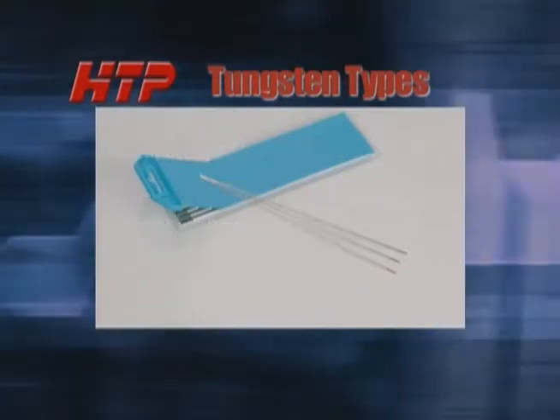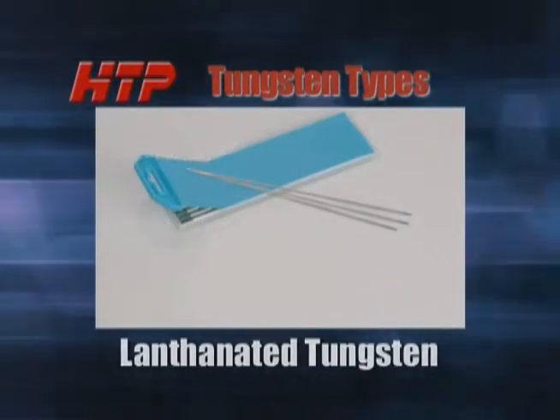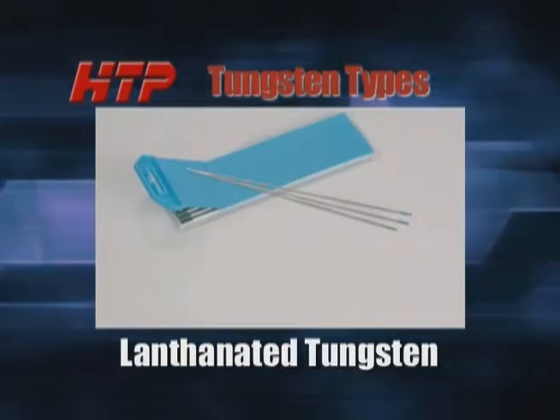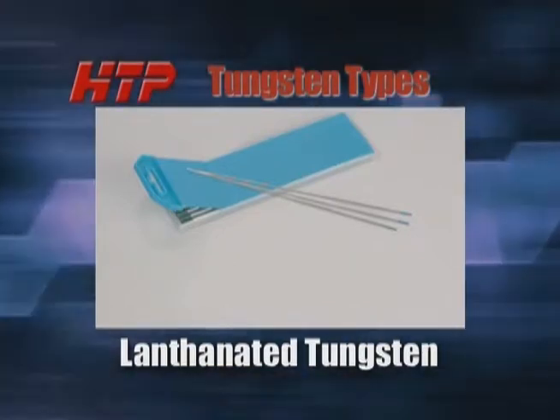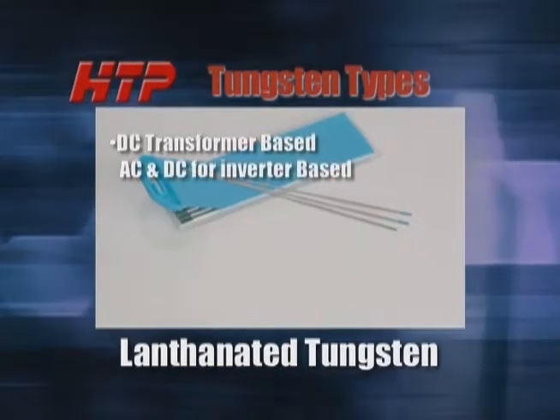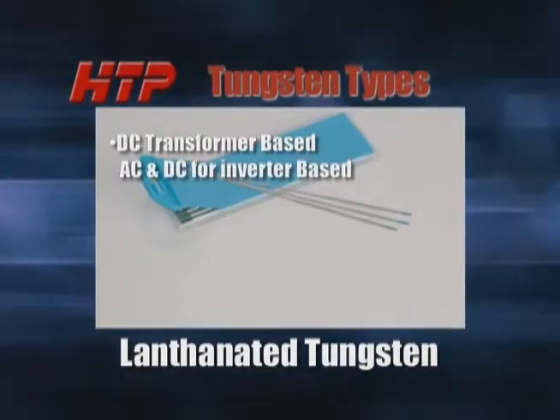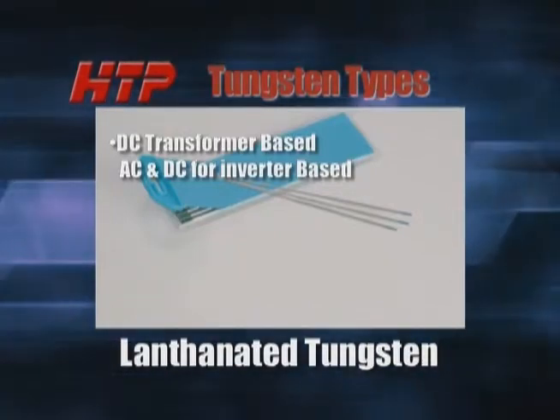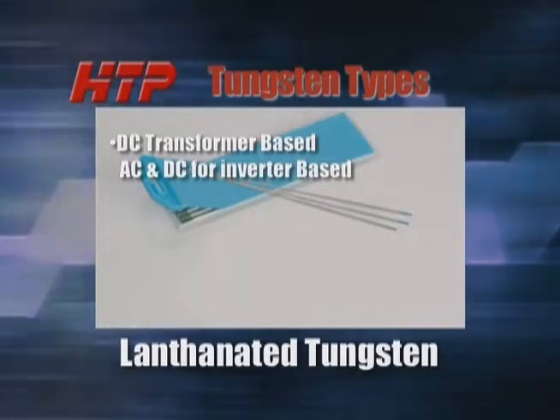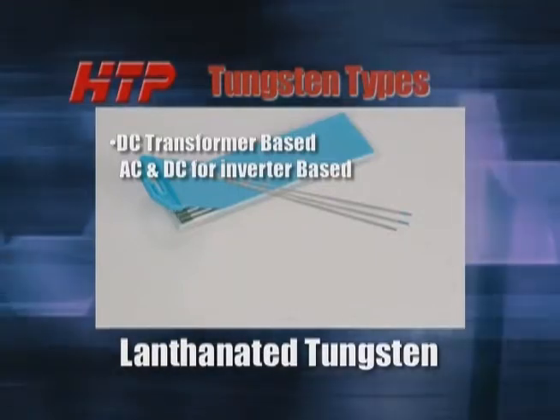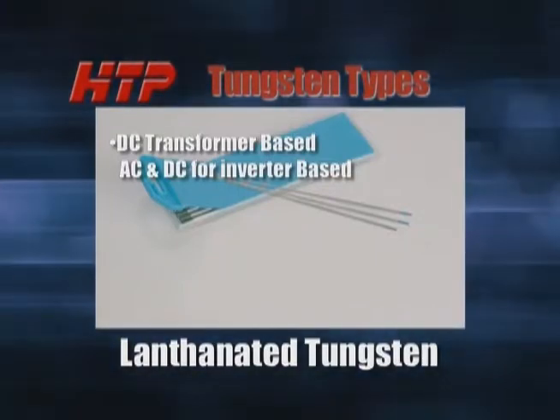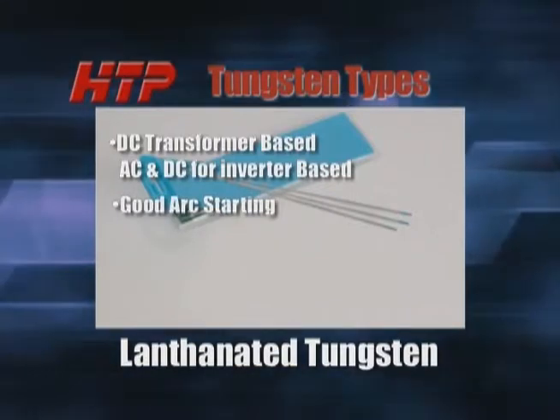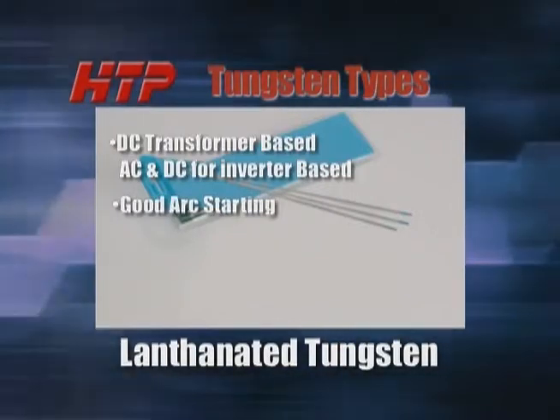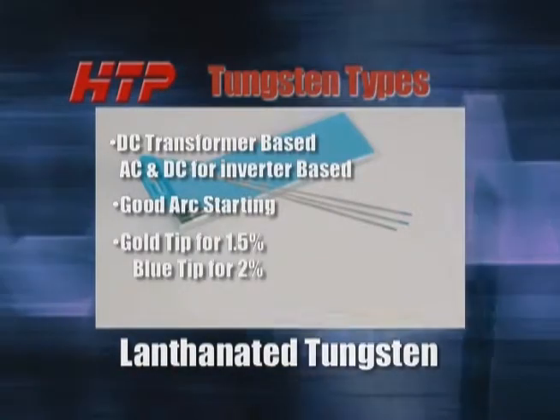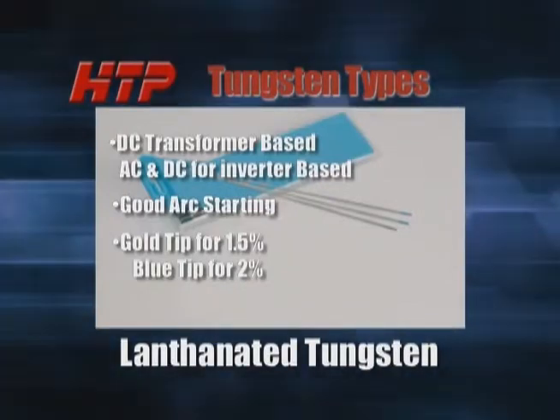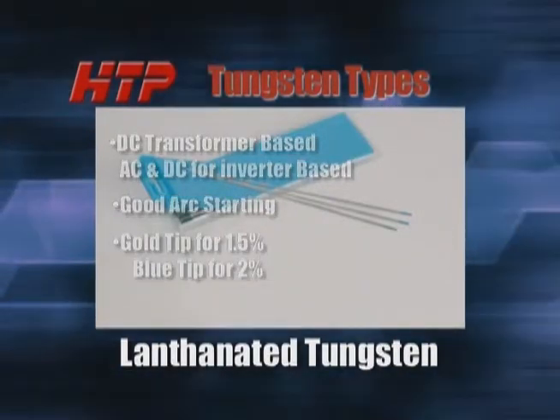Lanthanated tungsten is a good substitute for thoriated tungsten to eliminate the radiation hazard. It is generally used in the DC mode for welding steel and stainless steel on transformer-based machines and can be used for both AC and DC welding with inverter-based machines. It has a low erosion rate and gives you excellent DC arc starts. It's designated by a gold tip for 1.5% lanthanated and a blue tip for 2% lanthanated.